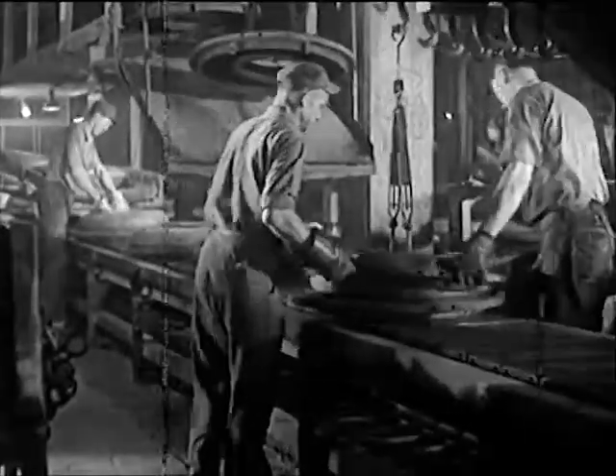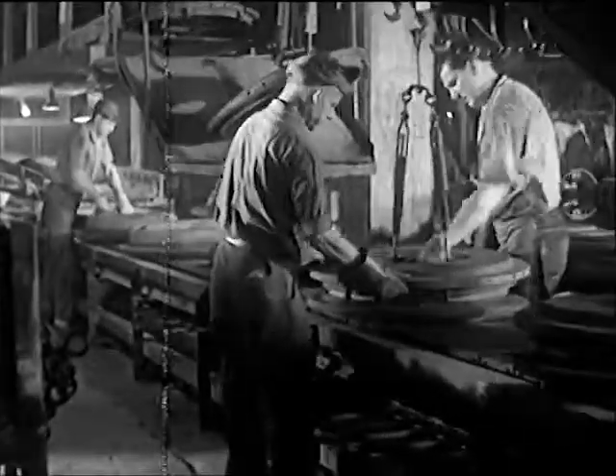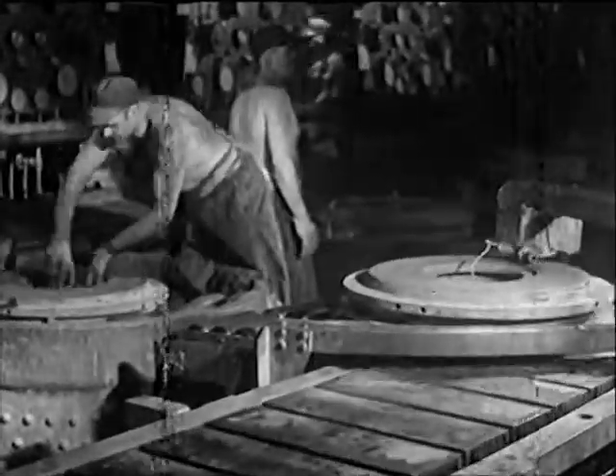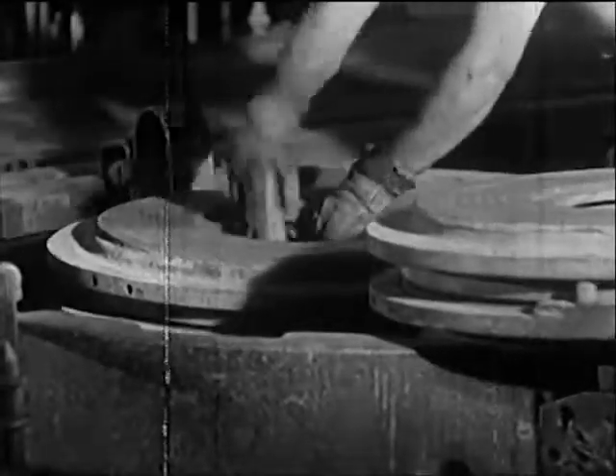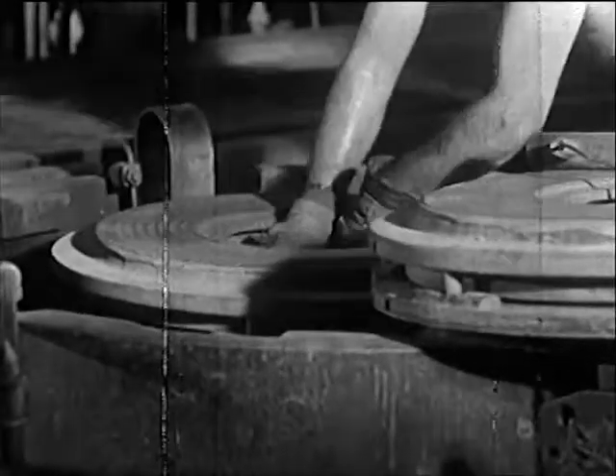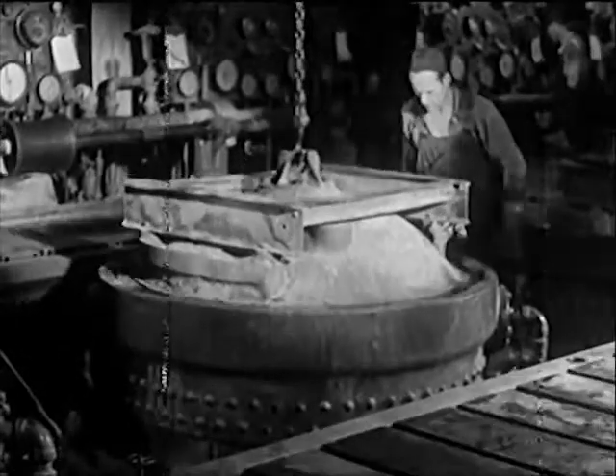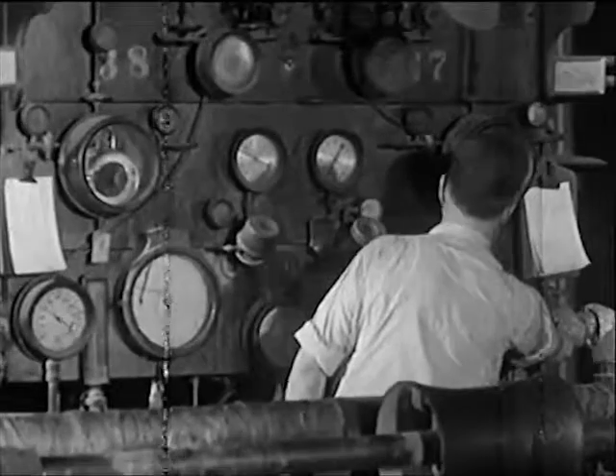After the tire is placed into the mold and the top half of the mold clamped down, it's lowered into a huge boiler, or vulcanizer, and a fitting is attached to the water bag inside the tire. Twenty-eight molds are placed in each vulcanizer, each mold fitted with a water connection. A hydraulic ram gradually lowers the molds as they're placed, and the water fittings interlock, forming a pipeline. When the vulcanizer is closed, water at a temperature of 300 degrees Fahrenheit and at a pressure of 240 pounds to the square inch is forced into the water bags inside the tires.